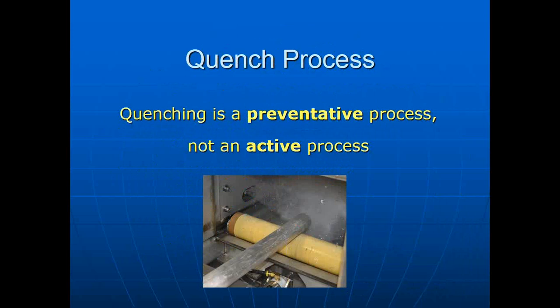The first and most important concept in press quenching of 6000 series alloys, which is very different than if you're coming, say, from the steel industry, is that quenching is a preventative process. It is not an active process. It does not give you properties. It prevents the growth of undesirable characteristics. And that sort of turns it on its head if you've done anything around quenching with steel, because quenching here is a purely preventative process. It accomplishes nothing, literally. But if you don't have it, you'll get something you don't want.